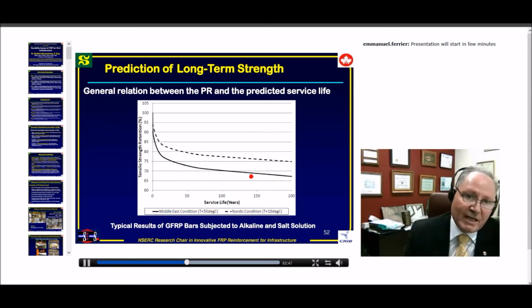And from this we can draw the strength retention as a function of the time. This is in years, and we can do it with any temperature. Here I draw it with like 50 Celsius and here 10 degrees Celsius, like an average annual temperature. It doesn't really mean that our material, when it will be in the field, will behave this way. I think what we observed from the field is the strength will not be as what we tested in the lab, because in the lab, of course, we used a very aggressive environment. But it will give really a very good idea, and of course it will be convincing to the engineer. And we can also, as you know, be very conservative, and this is what we have in our code by specifying the reduction factor that will take into account such results from the lab.